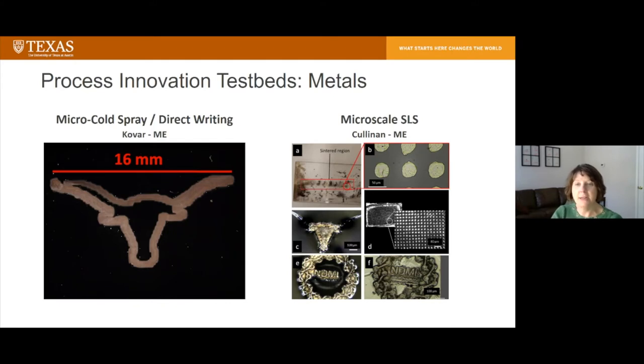Cullinan in mechanical engineering and his collaborators. This process is really aimed at very, very small scale metal features. So if, for example, you'd like to apply additive manufacturing to micro or nano manufacturing applications, like wafer scale interconnects, it's really impossible to do that because most commercial machines have feature sizes that go as small as maybe 50 microns. It's usually larger than that. But you need much smaller feature sizes here. And so this process will actually give you 5 micron metallic features at high speeds.